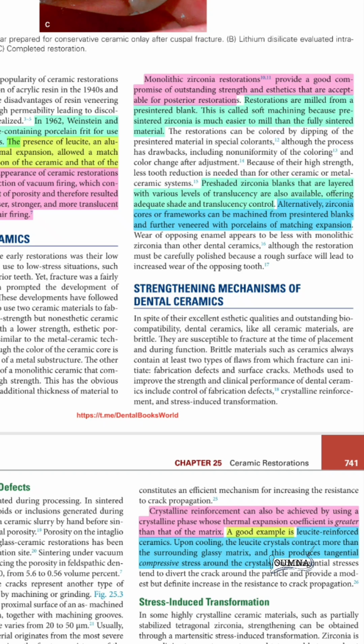the atoms are close to each other before reaching the melting point. Soft milling is for the pre-sintered, which is the most common, and hard milling is for the sintered zirconia, but it requires the equipment to be more rigid, so some micro cracks may happen in the zirconia core during the manufacturing, which will decrease the physical and mechanical properties of the zirconia. So soft milling is the common way to manufacture the zirconia.